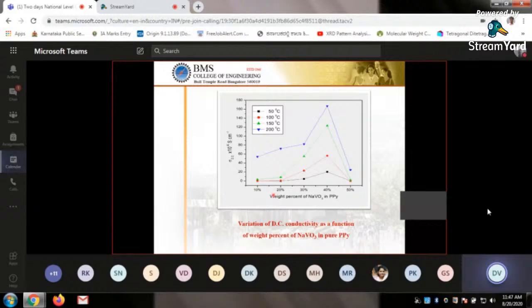If you plot a graph of weight percentage with conductivity at different temperatures, the black line is 50 degrees centigrade, red is 100 degrees centigrade, green is 150 degrees centigrade, and blue is 200 degrees centigrade. Now look at all the lines. As temperature increases, conductivity increases, but it is more for 40%. So this percentage we assigned as the percolation threshold. Below this percentage the conductivity is less, and even after that the conductivity is less. So for our composites, we proved that 40 is the best because its conductivity is good and other properties are also good. So if you want the conductivity at this temperature, this value, then you can use these materials.